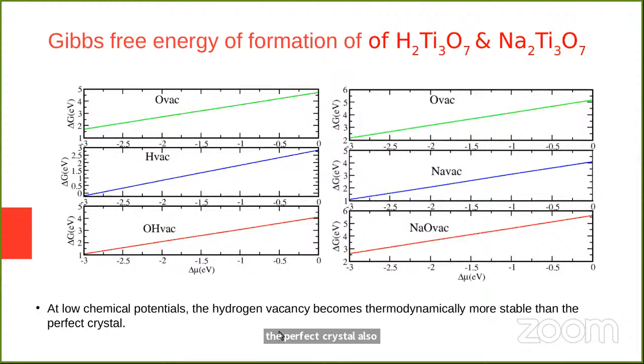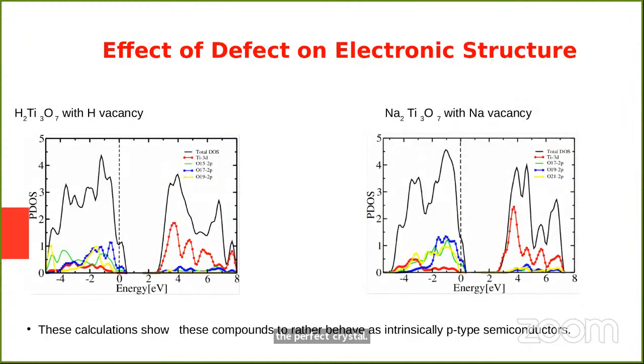Also, we studied the effect of defects on the electronic structure. And we found that the defects have an important effect on the electronic structure in both cases. The Fermi level moves below the top of the valence band, leading to holes being the majority carrier, as a result of the defect. And from this calculation, we expect this compound to become an intrinsically p-type semiconductor.